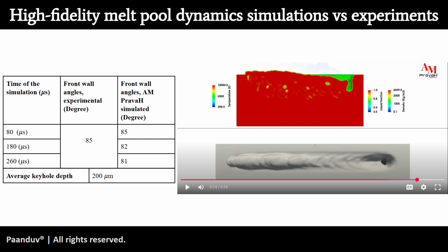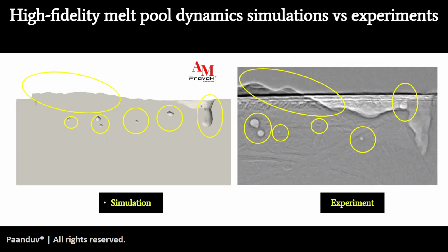And what we are seeing at different times from the simulation, at 80 microsecond we are seeing 85 degrees, at 180 microsecond we are seeing 82 degrees, and at 260 microsecond we are seeing 81 degrees. Average keyhole depth is 200 microns, and we are also observing very similar depths in our simulations as well, around 200 microns. So very nicely matching the experimental data despite all the complicated physics that goes behind it.